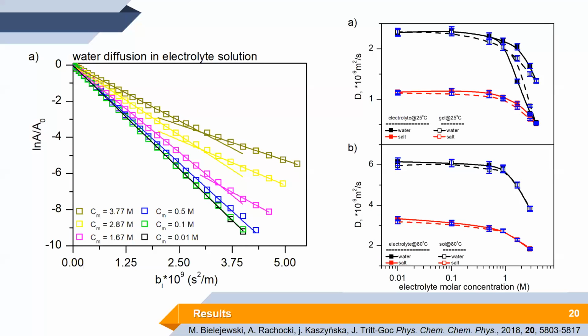The second point is that when you look at the dashed lines, which stand for the data obtained in the gel phase, we see that the diffusion coefficient, although the system turns from liquid to solid-like, is very similar to what was observed in the liquid state, although still a bit smaller. So, in principle, increased diffusivity of the ions or other liquid molecules cannot support the increased conductivity. So this was something we expected. First, that we don't get the answer in that easy way, but also that decreasing the diffusivity of the molecules when we go to more restricted motions is something we would expect.